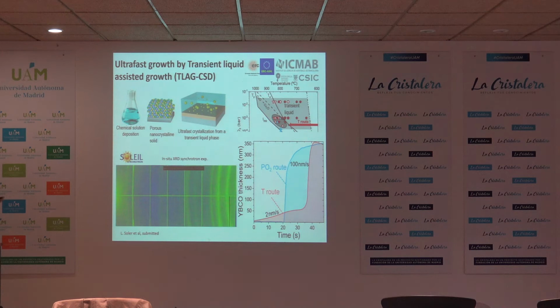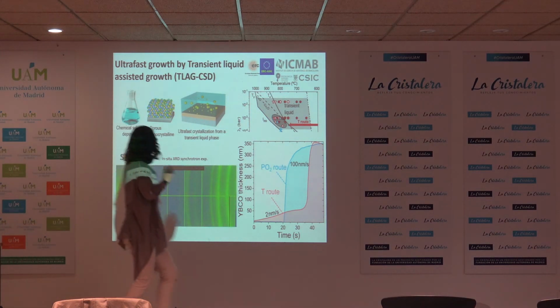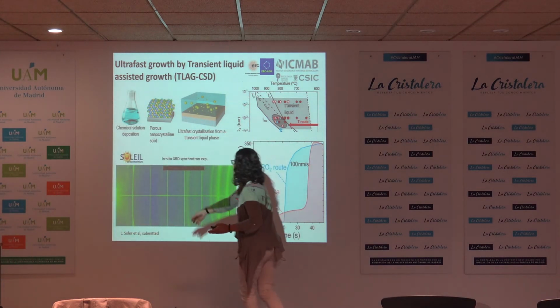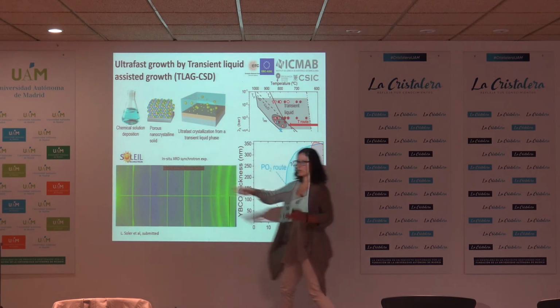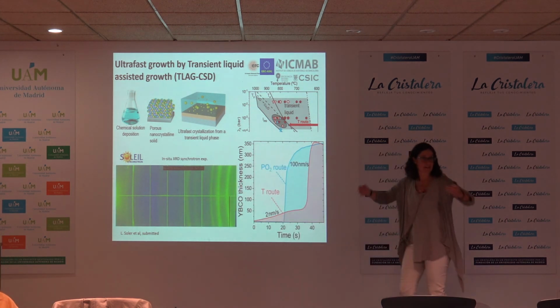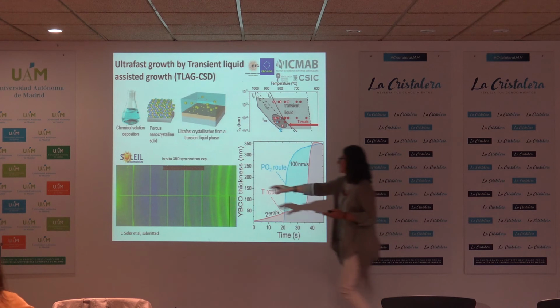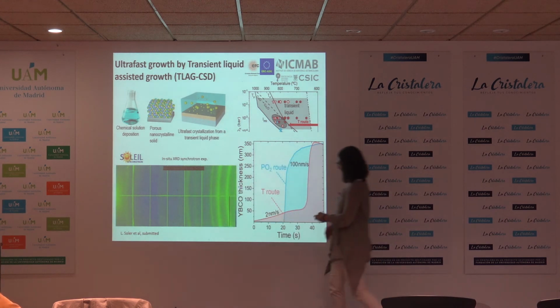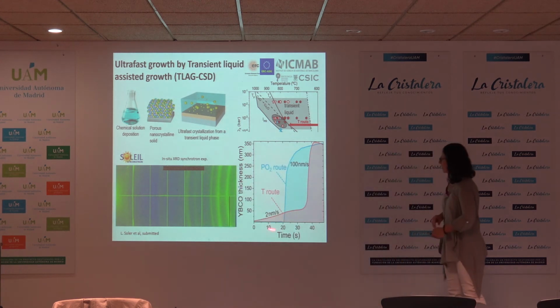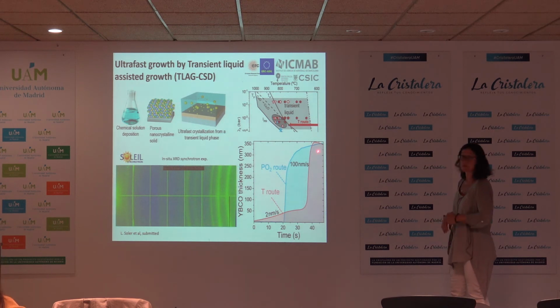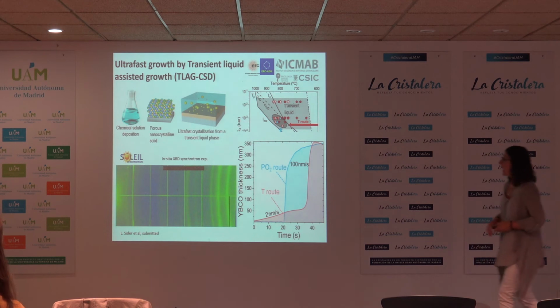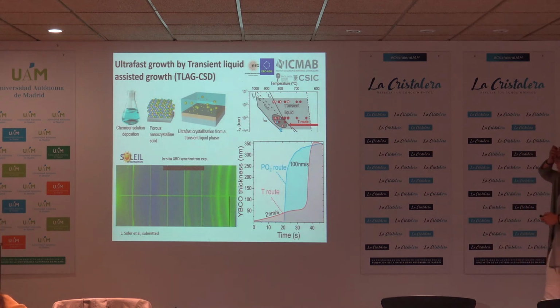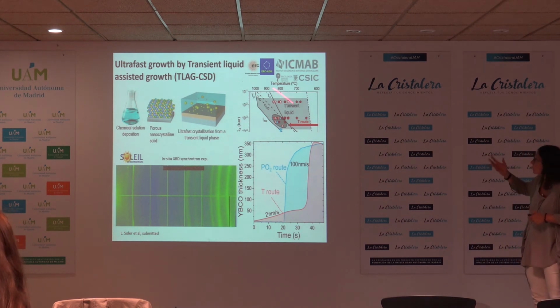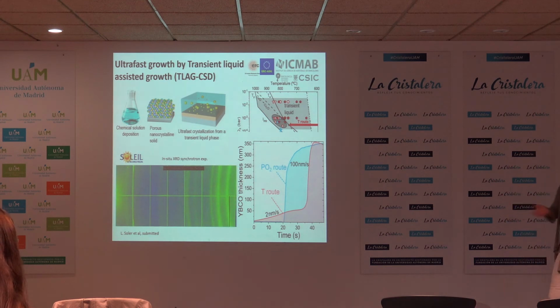Well, anyhow, the situation is this is a theta to theta scan where you can see how the different phases are reacting, and at the end, very fast, you get the peak of the YBCO. In fact, this is the integration of this signal, and what you can see is that we can grow YBCO at 100 nanometers per second. And these experiments at the synchrotron were done emulating this process, acquiring images every 100 milliseconds.